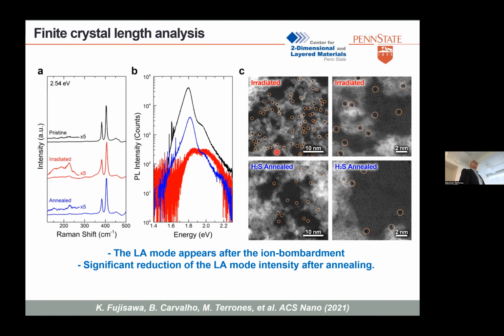One thing we did afterwards: after we irradiated, we then annealed it in H2S. We passivated with H2S, and after irradiation we could see that some of the defects annealed, and we can see the recovery of the PL as well. The irradiated one has suppressed PL, but the annealed one has a PL that is being recovered. So you can anneal the defects as well. So maybe a way to process a sample where you want to anneal defects is to put it in H2S and make it more perfect.